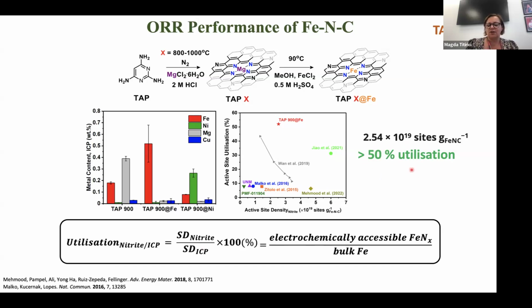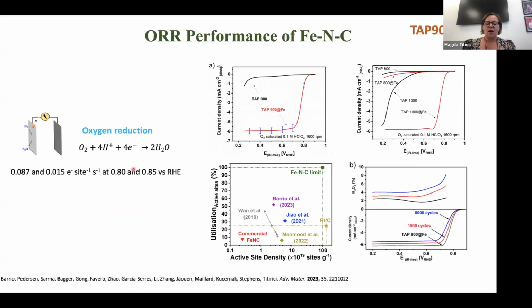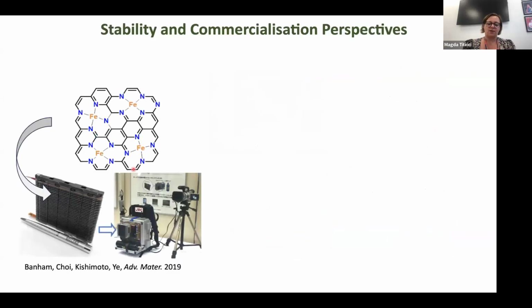And this is how you're going to learn that in fact, our catalyst does not have a very high active site density, but most of the sites that we have are extremely active. 50% of them are very active, which is quite good. And this is in an acidic environment where normally this reaction does not work. So as I said, this works very well.